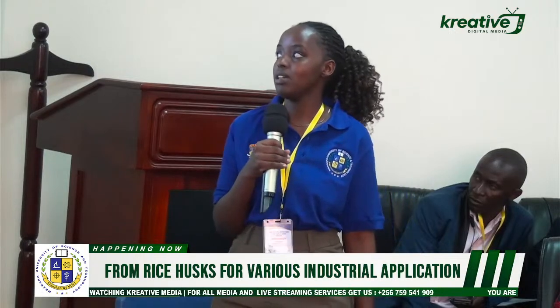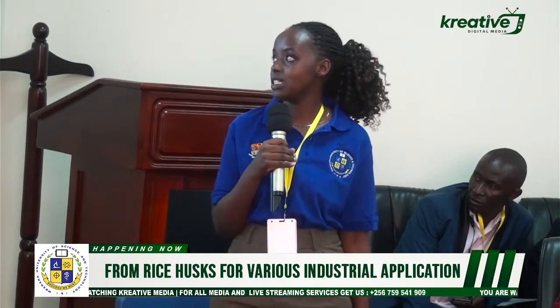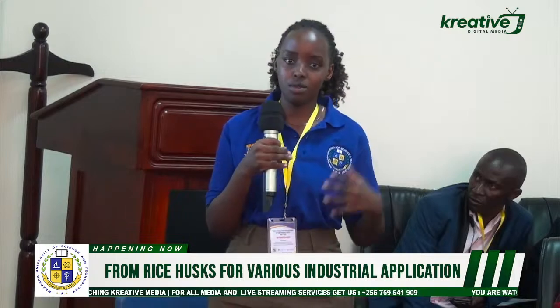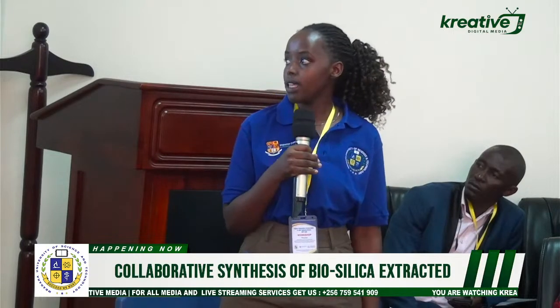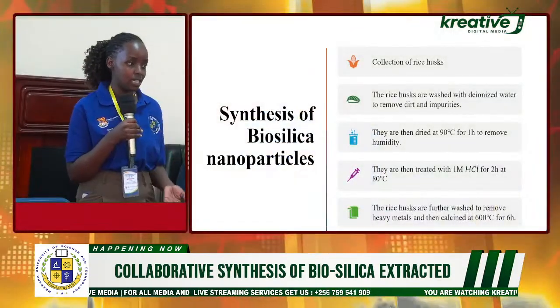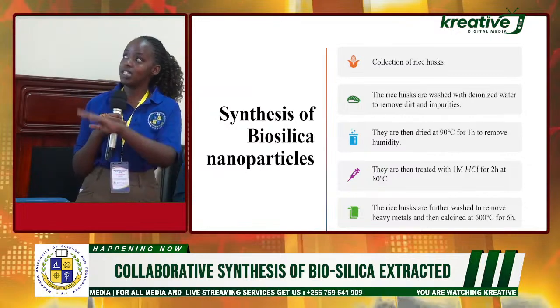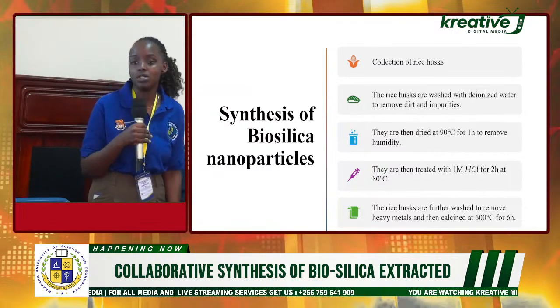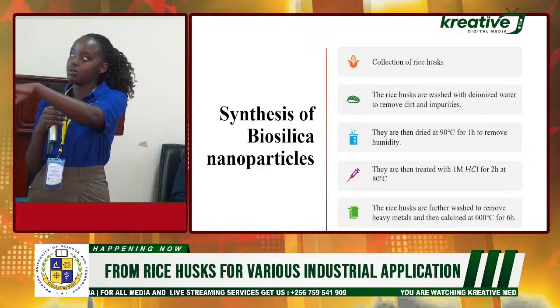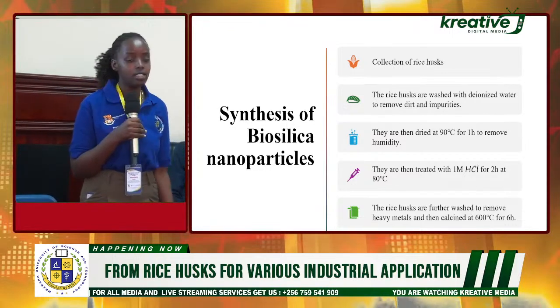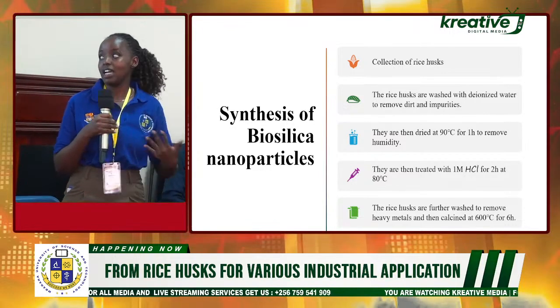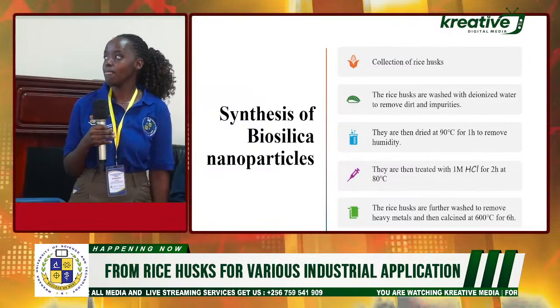After washing them, they are dried at 90 degrees Celsius for 1 hour. That is to remove the water. That is followed by pre-treatment with an acid. Usually, here we're using HCl. What is the importance of pre-treatment? That is to remove metallic impurities. Usually the rice husk has impurities which cannot be removed by just water. So these ions dissolve in the acid and then they can be retrieved.